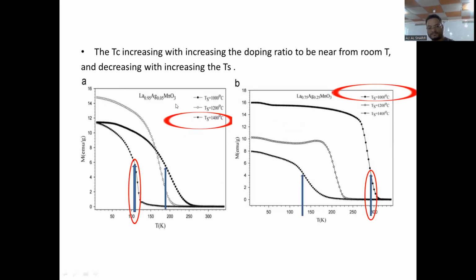Now, at doping ratio equal 0.05, here it's approximately 287 at 1000 at the first sintering temperature. At the first sintering temperature at doping ratio equal 0.25, it's near room temperature. But in both of these two images, by increasing the sintering temperature, the Curie temperature will be far away from room temperature. That means it's a disadvantage here.